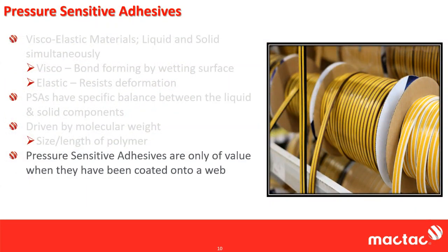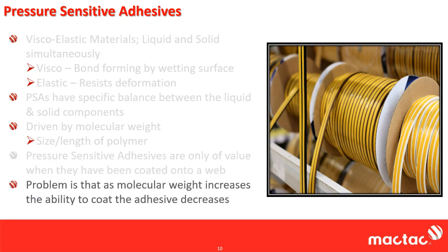And again, everything that we're covering here is really driven by the fact that we need to coat the pressure sensitive adhesive onto a web. That's where it's getting its most value. The problem, and why I'm talking about molecular weight, is that in order for the adhesive to be of the proper molecular weight, so that you can make a bond and hold a bond, it makes it very uncoatable. It's not really very easily coated. In some cases, it's impossible to coat. So how do we get around that?